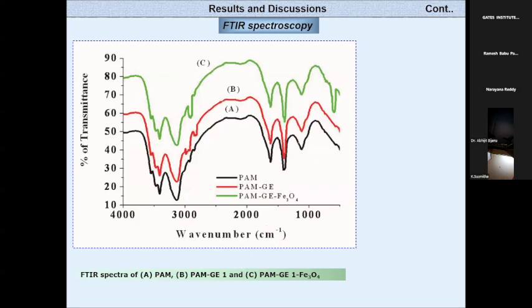Like I said, we want to see if there is any variation due to the magnetic nanoparticles. We are giving FTIR spectroscopy to compare the spectra of regular PAM, PAM-based gelatin, and PAM-based gelatin with magnetic nanoparticles. This is a fingerprint spectrum, where you can confirm the presence of acrylamide polymer units, gelatin units, and magnetic nanoparticles in your system. This green peak indicates Fe3O4, which corresponds to the incorporation of nanoparticles into the hydrogel network.